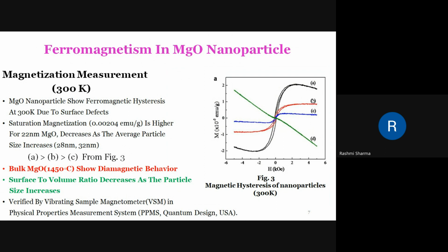From this graph, it is clearly visible that the 22 nanometer particle shows a sharp ferromagnetic hysteresis curve. And when the size is increasing, we do not get this curve. When we reach the size of the bulk sample, the ferromagnetic hysteresis is completely lost.